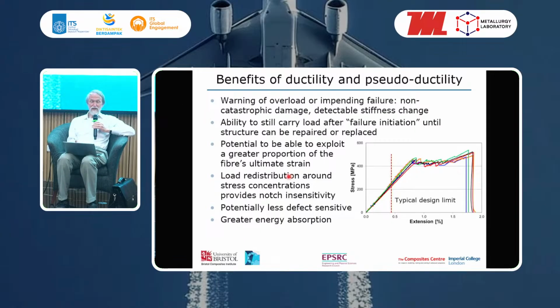Currently, if you look at the stress-strain response, carbon fiber composites are very limited. We've got materials which can go to about 2% failure strain, but typical design strains are more like about 0.4% strain. Our idea is that we can go beyond that and get closer to this knee point. We wouldn't want to operate above this knee point, but you could get much closer to that knee point and hopefully push that design strain further up. And also get greater energy absorption. And one of the things we've been doing recently is looking at using these hybrid materials to try to improve the penetration resistance of casings for aero engines.